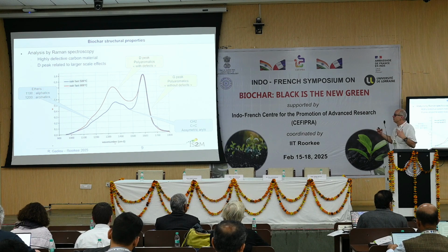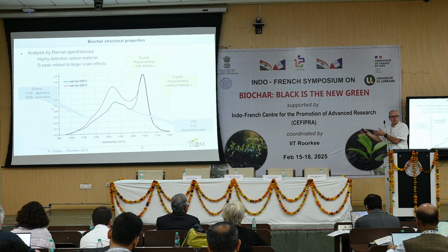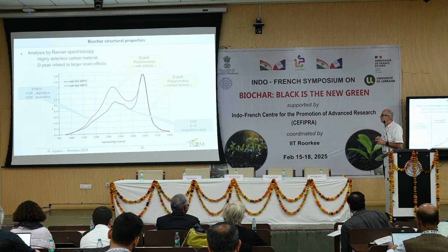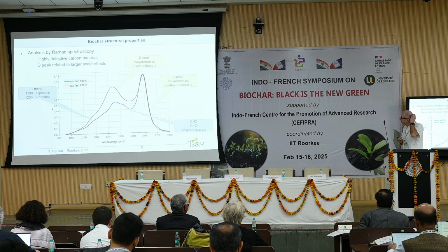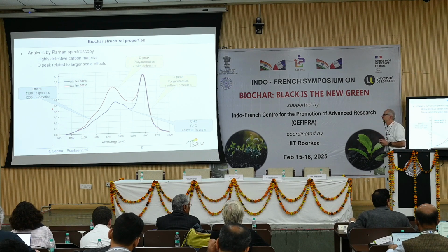Bond level is a functional group, and to observe functional group easily in biochar, you have to work up to 400 Celsius degrees, for example. At 500 Celsius degrees, it's very difficult to observe nice NMR peaks, so it's more complicated.